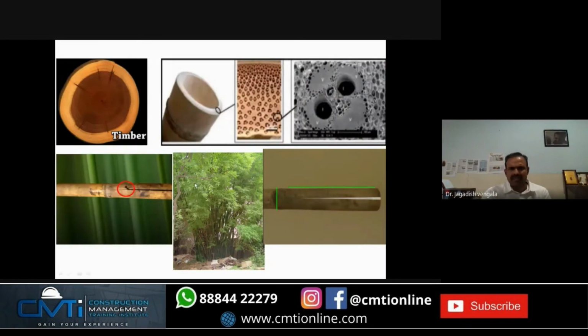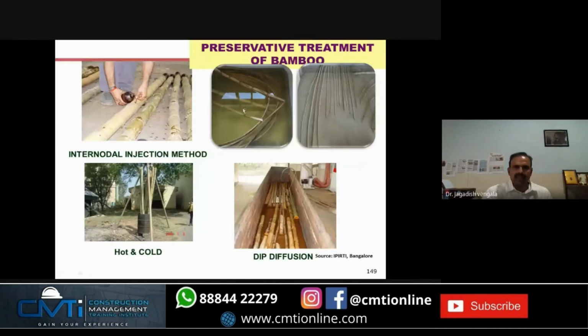Bamboo comes under grass, and when you compare with timber, it has different properties. Like in timber, you have the radial fibers. Here you have fibers which are oriented in the axial direction. So you split it and then you treat it, because as a reinforcement we have treated the bamboo.